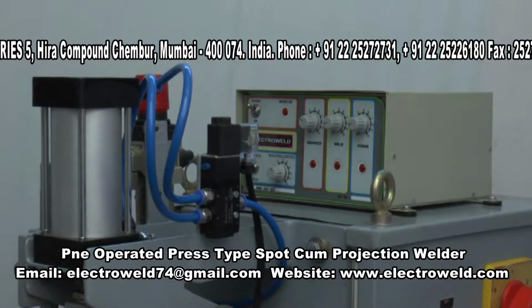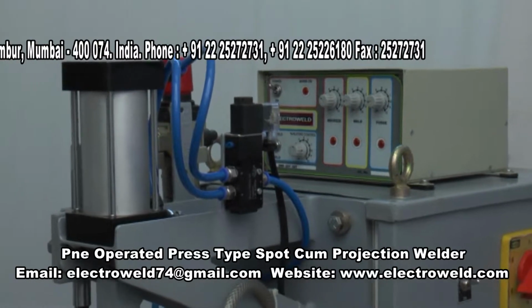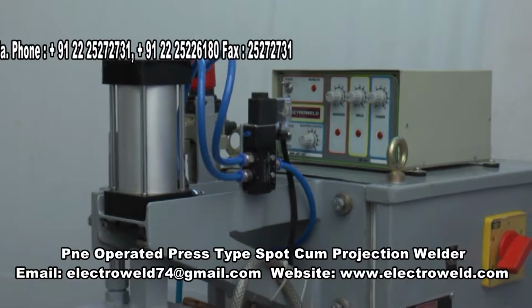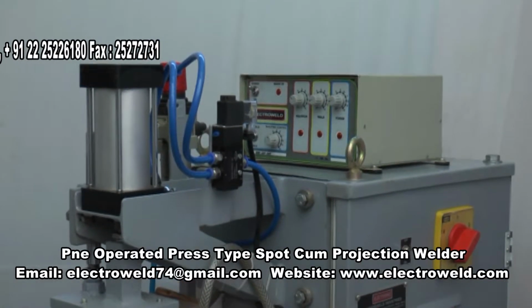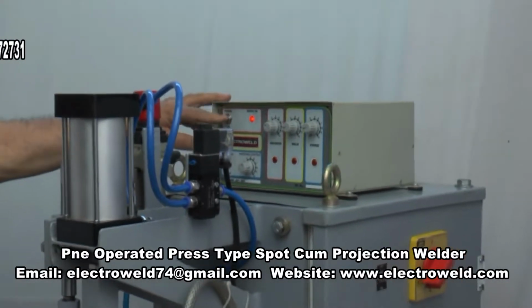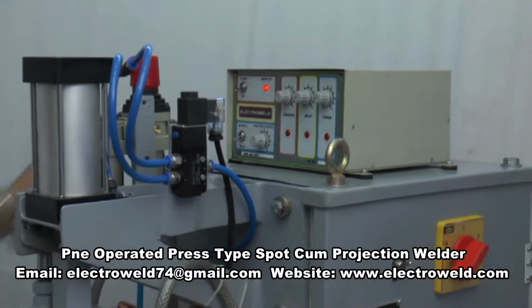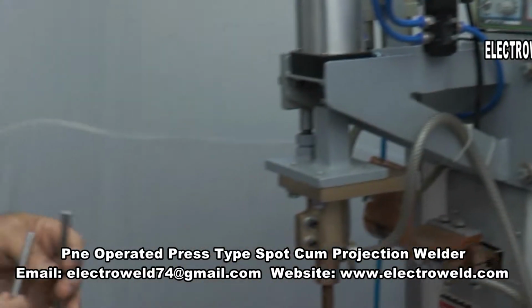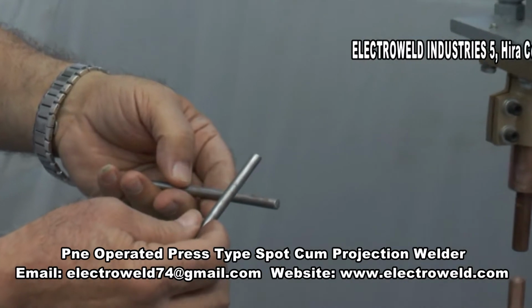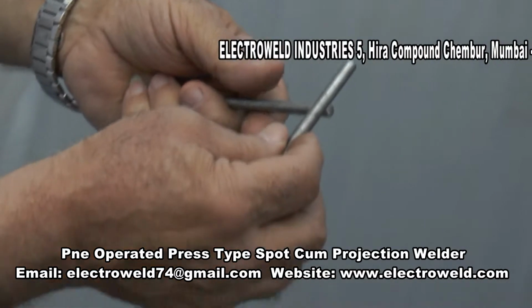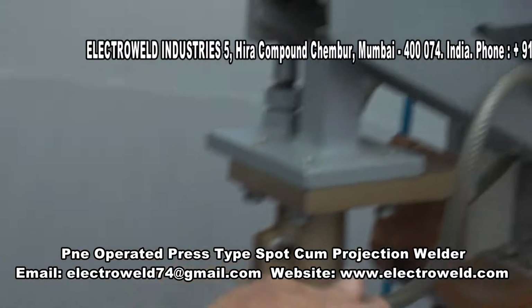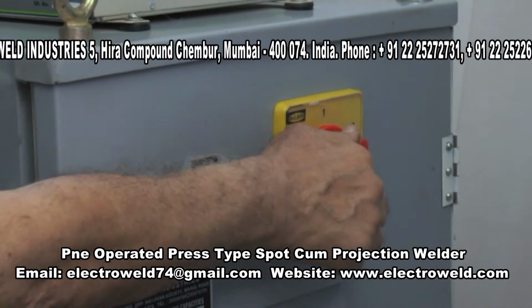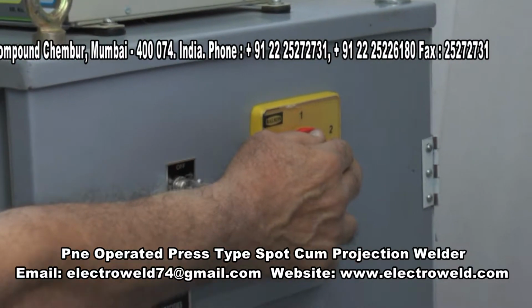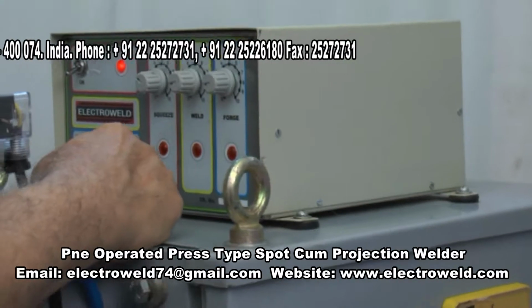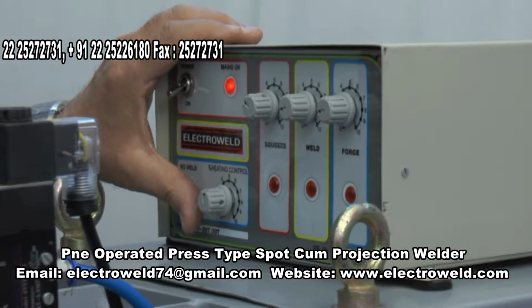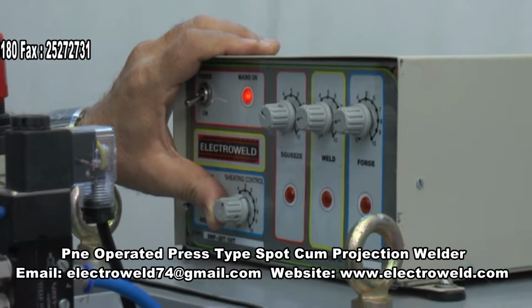Thank you. On this machine you can also weld kitchen baskets by overlapping rods over each other. First we will switch on the power supply on the timer. Then, supposing we wish to weld 6 mm plus 6 mm rods of SS for kitchen baskets, first we have to adjust the current. So keep it at number 3. Again the fine current rating knob, you can keep it at say number 6, that is 60% of the particular